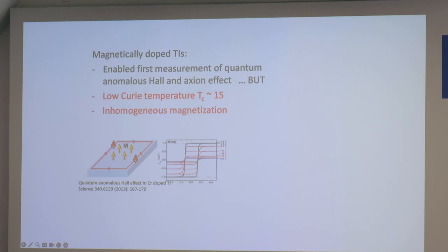And also, when you dope these materials, you do add disorder. You add a lot of disorder by just adding carriers in these. You get inhomogeneous magnetization, and you get other effects that reduce your quantization and reduce the beneficial effects of magnetism that you want. So an alternative to magnetically doping TIs is to proximity magnetize them. Instead of putting magnetic adatoms in, you just put the material close to a magnet and hope that you get leakage of magnetism and you can magnetize a surface state that way.